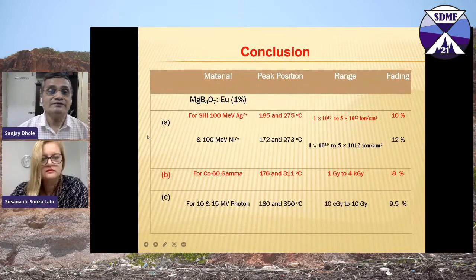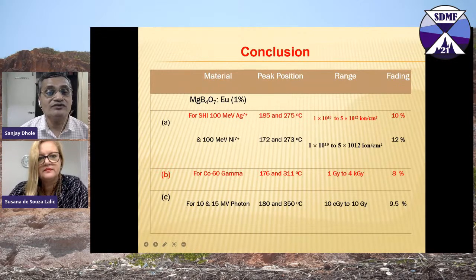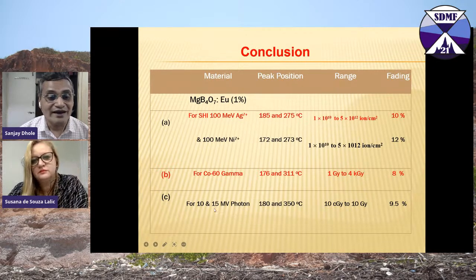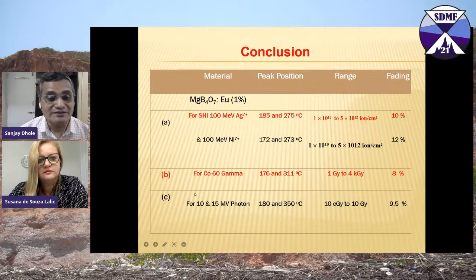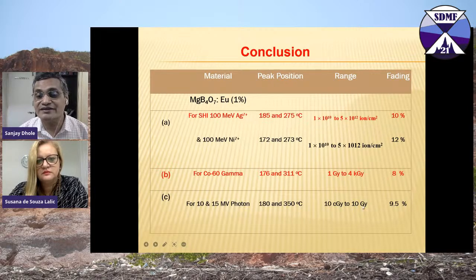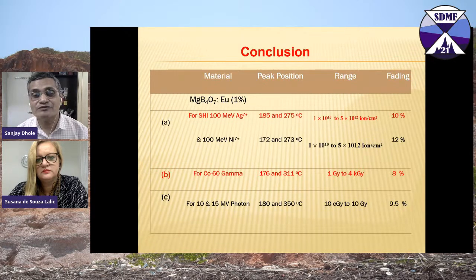So in conclusion, the material that we could develop here, the magnesium borate doped with europium, that we have taken 1%. Swift heavy ion, that is 10% fading. Okay. And for cobalt 60, it is 8% fading, but the dose range is 1 gray to 4 kilo gray. And this 10 MV and 15 MV photon, these photons are being used for the cancer treatment, where you can measure the dose using this particular phosphor is 10 centigray to 10 gray, and the fading is still less than 10%, that is 9.5%.